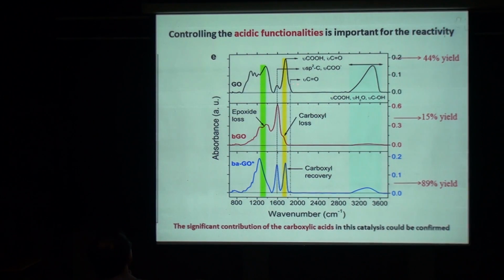We can prove this by FTIR spectroscopy. Now, if you get a graphene oxide, you can see this COOH group. The moment you react with a base, the base will transform the COOH to a carboxylate, CO minus Na plus. Once you transform to a carboxylate with the proton disappearing, straight away this peak disappears, you find that the catalytic activity declines dramatically. Then you do a base neutralization. You introduce an acid again, so you have carboxyl recovery. Then your catalytic activity improves. This tells us that you need the carboxylic group to be COOH and not COO minus. So this COOH group is very important. If you neutralize it with a base, forming the CO minus Na plus, it's not going to work.